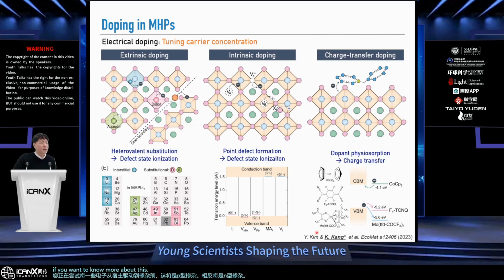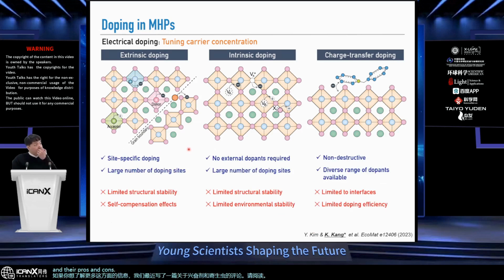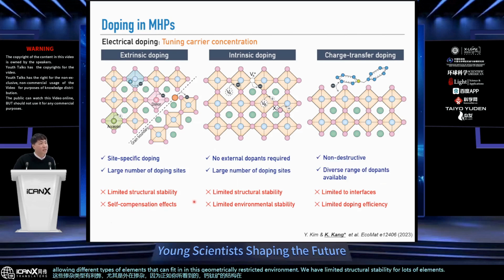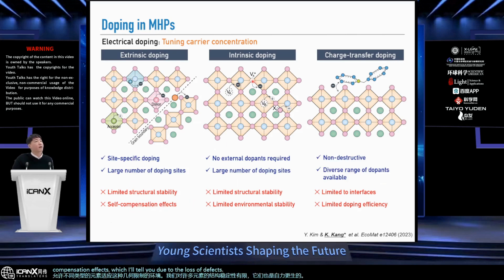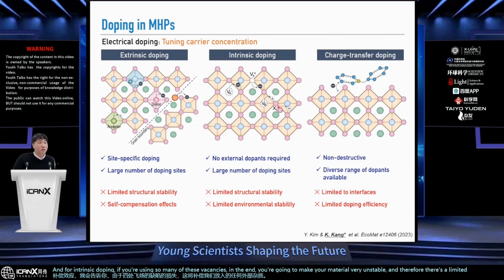If you want to know more about this, there's a recent review that we wrote on doping in perovskites, so please have a read. And there are pros and cons with these doping types, especially the extrinsic doping, since, as you can see, the structure of perovskites is quite restrictive in terms of allowing different types of elements that can fit in this geometrically restricted environment. You have limited structural stability for lots of elements, and there are also self-compensation effects, which I'll tell you about, due to the lots of defects that are flying around, and that will compensate for any external impurities that we put in. And for intrinsic doping, if you're using so many of these vacancies, in the end, you're going to make your material very unstable. And therefore, there's a limited range of how you can use this intrinsic doping.